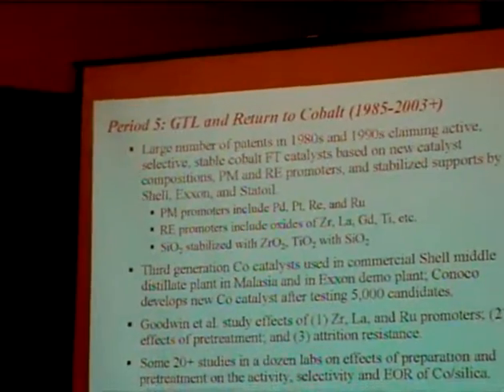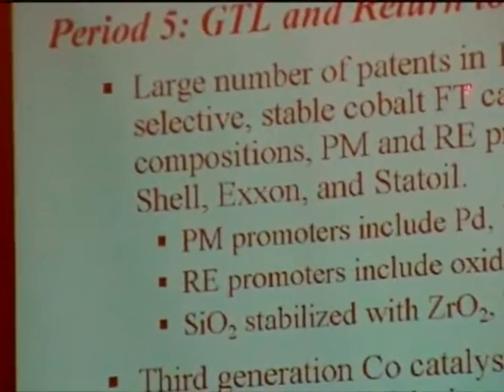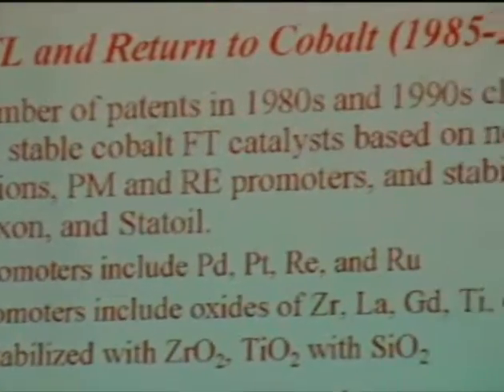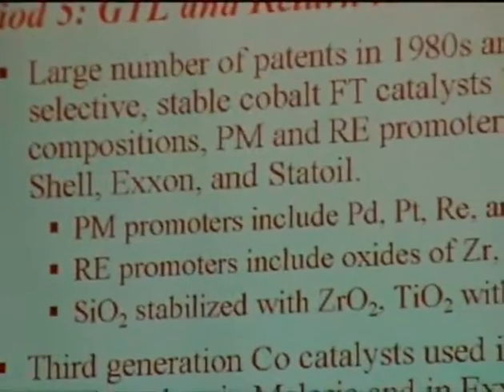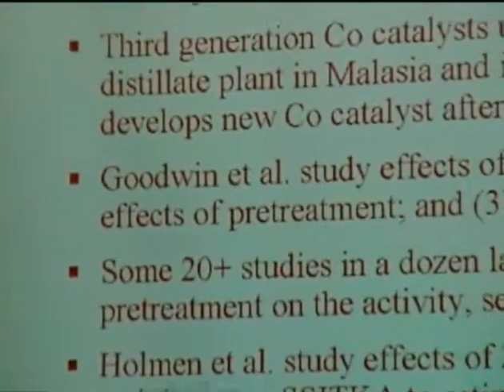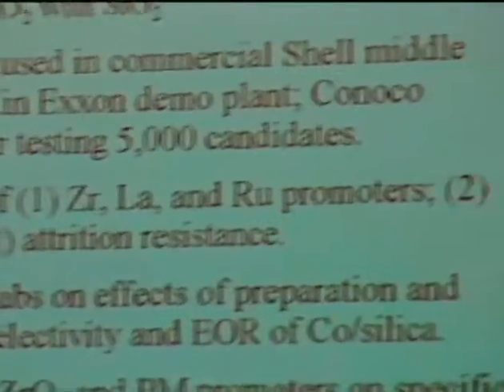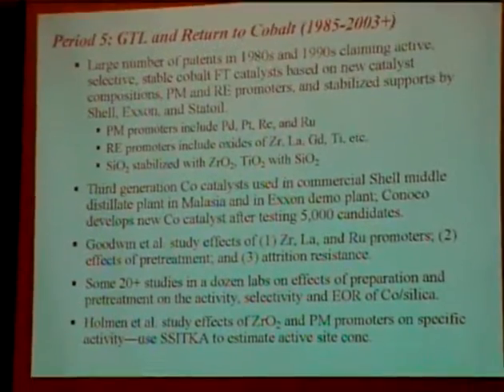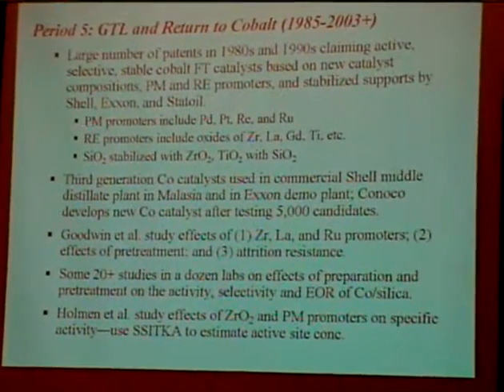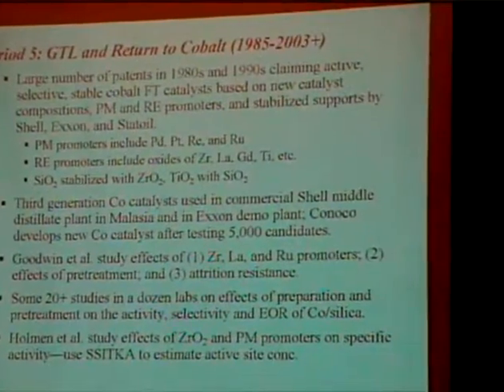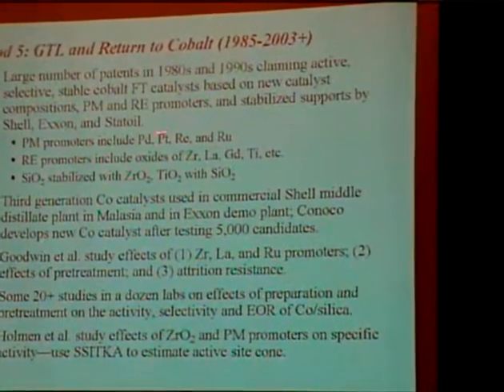Now we come to period 5. This is GTL and the return to cobalt, starting in about 1985. In the 80s and 90s there were a large number of patents claiming active, selective, stable cobalt FT catalysts, based on new compositions, precious metal and rare earth promoters, and stabilized supports, by Shell, Exxon, and Statoil. Some of the precious metal promoters include palladium, platinum, rhenium, and ruthenium.